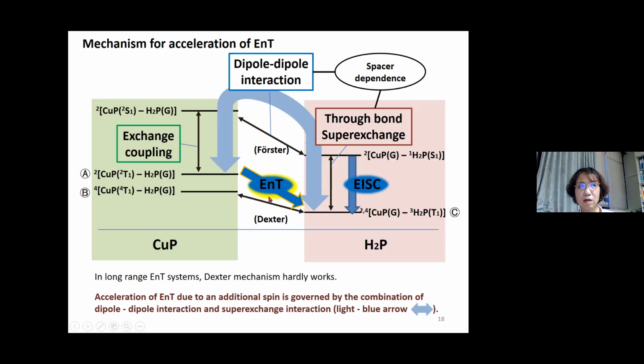Actually, these figures explain the difference between energy transfer and enhanced intersystem crossing, because enhanced intersystem crossing is controlled only by the through-bond superexchange interaction, but in energy transfer cases we have dipole-dipole interaction, which is controlled by the distance, but also by the superexchange interaction. So the acceleration of the energy transfer due to the additional spin is governed by a combination of the dipole-dipole interaction and the superexchange interaction.